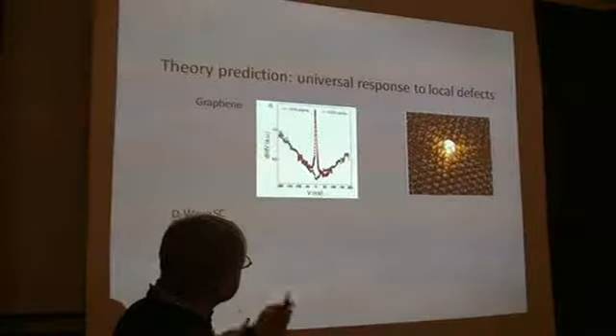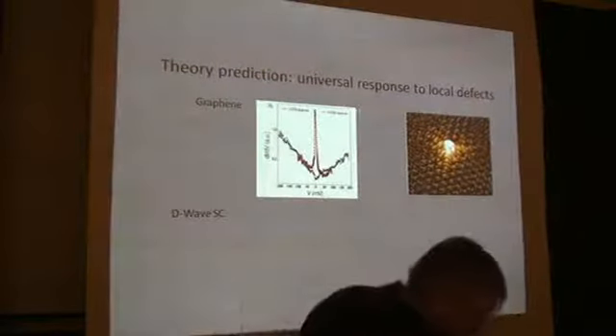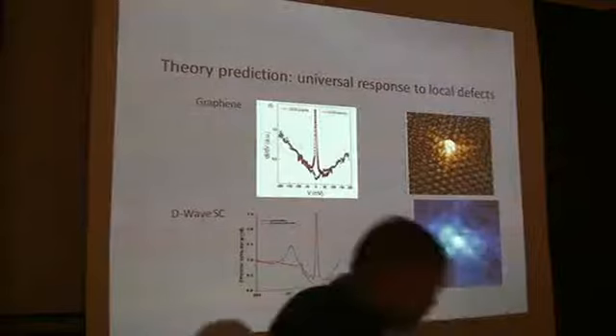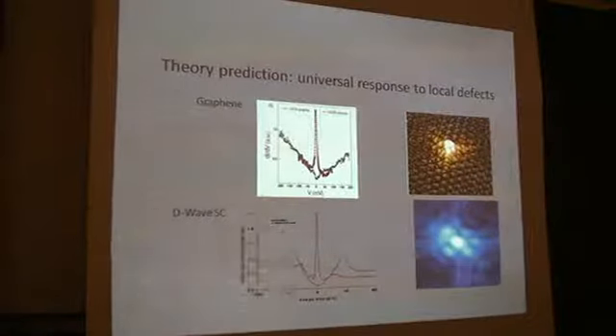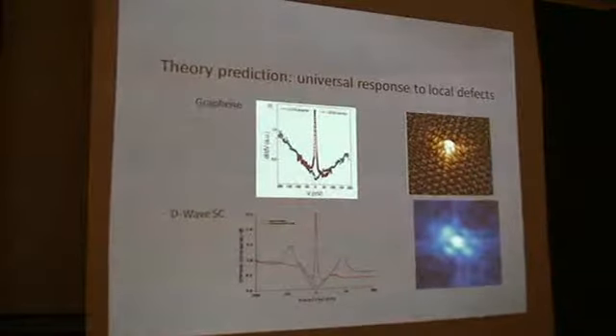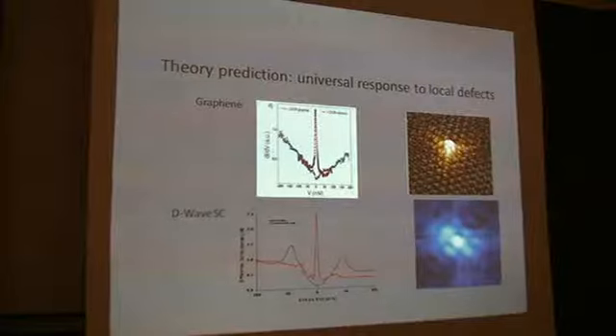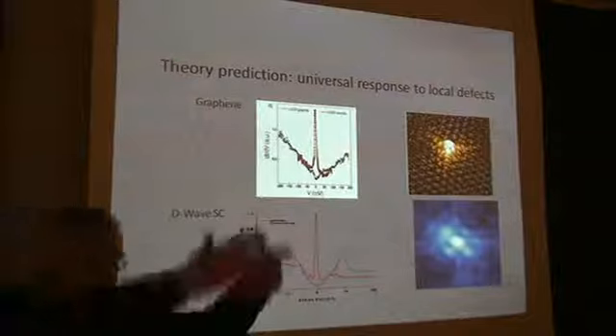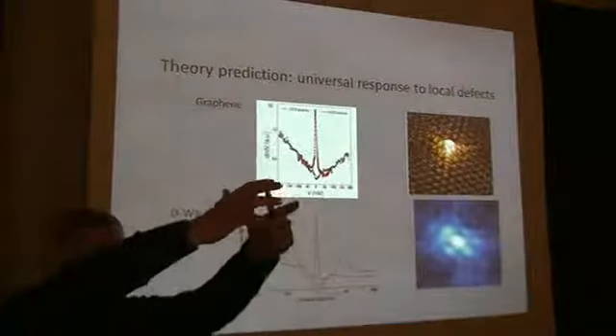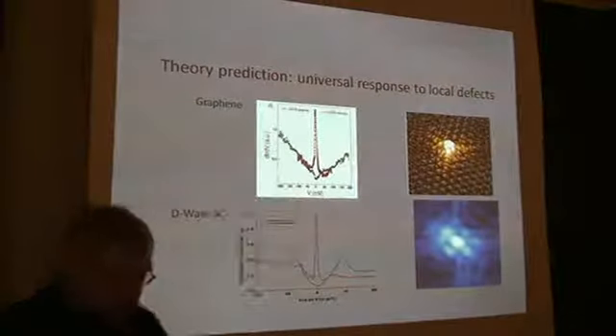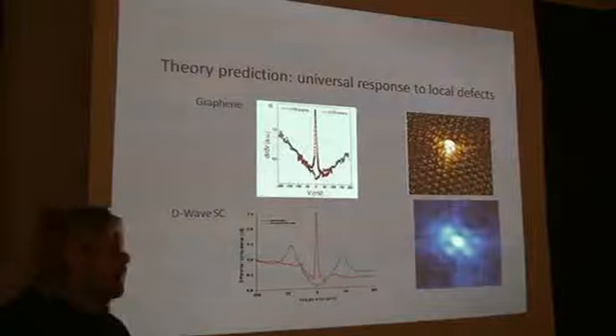Okay. So what I showed you is actually in the theory and an experiment. In fact, you do see the reasonable response. I have a Dirac-like distortion and defects produced inside it. These resonances are localized states, or nearly localized states. Those are scattering states, but they produce this pile up of intensity, which is localized. It's not moving anywhere. It's like a sand pile on the beach.